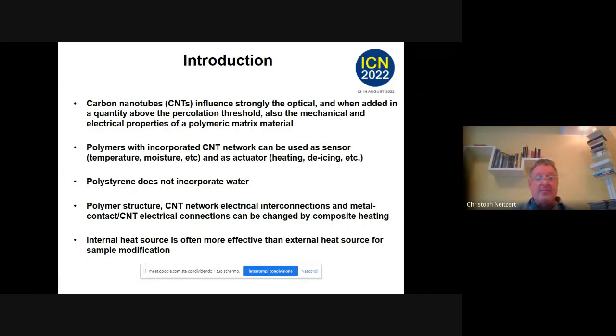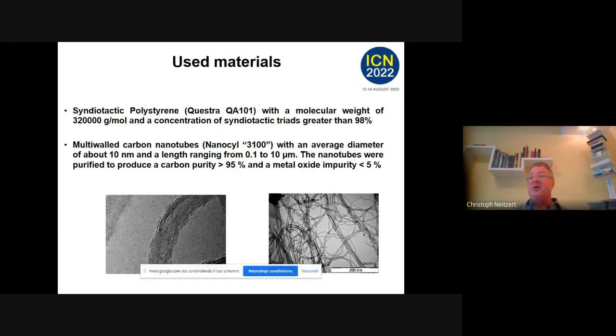No? The polymer structure, the CNT network electrical interconnections and metal contact carbon nanotube electrical interconnections can be changed by heating. No? So if you make a heater, you may change them during operation, or you have a sensor as well. So you have to stabilize them in some way. No? Internal heat sources are often more effective than external heat sources for sample modification. No? You can use this even for crystallization. You can use the nanotube conduction for example in the preparation of an epoxy nanotube composite for the curing procedure. You can cure it by Joule heating.